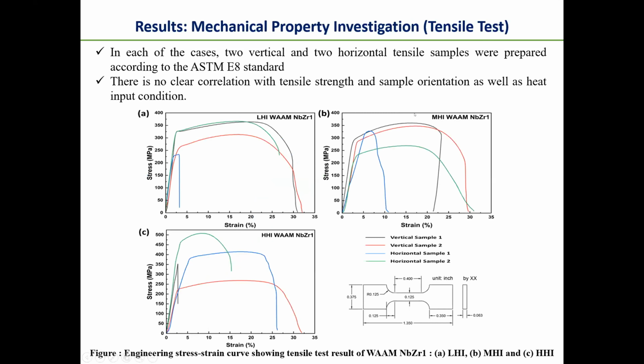For the mechanical test, we performed the tensile test in each condition. We made 4 tensile specimens for each condition, 2 in the vertical and 2 in the horizontal direction, all according to ASTM E8 standard. We did the tensile test, but we could not find any correlation in the tensile strength with respect to the sample orientation as well as the heat input condition.